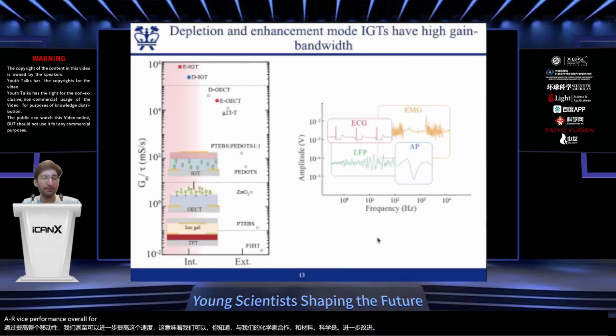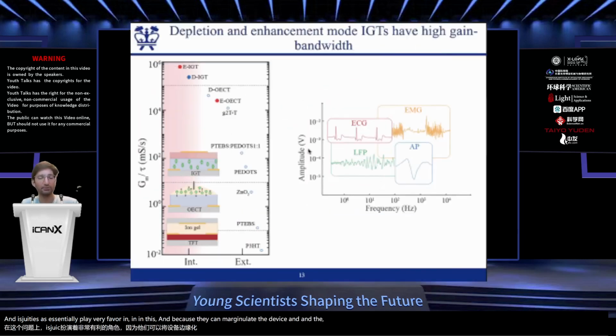Overall, for an effective neural interface pre-processing unit, you need both speed and amplification. And these IGTs play very favorably in this regard because they can modulate the small neurophysiological signal with their high transconductances while maintaining a high speed. In fact, it allowed us to record the entire physiological spectrum from EMG, muscle activity, heart, ECG, all the way to local field potential as well as individual action potentials.